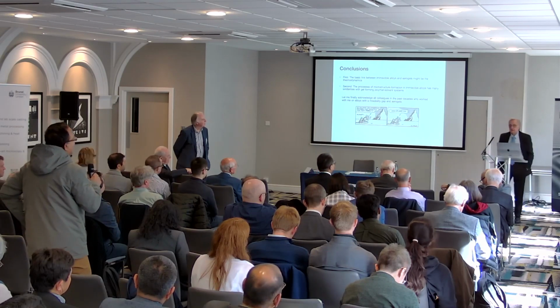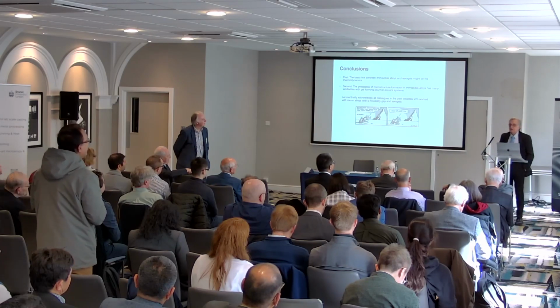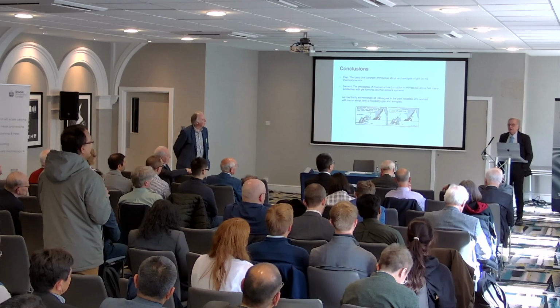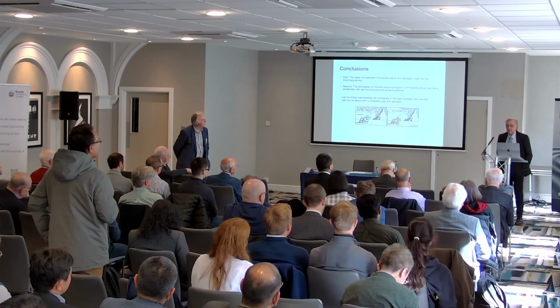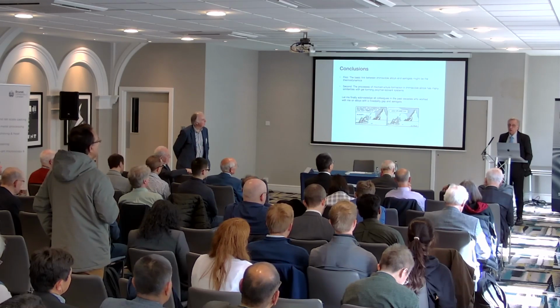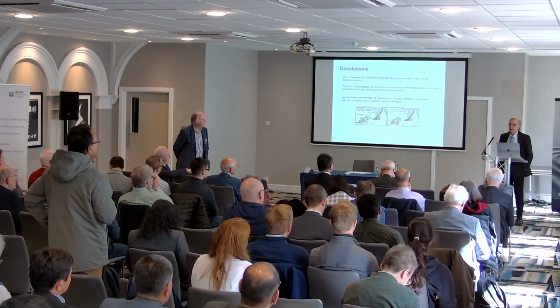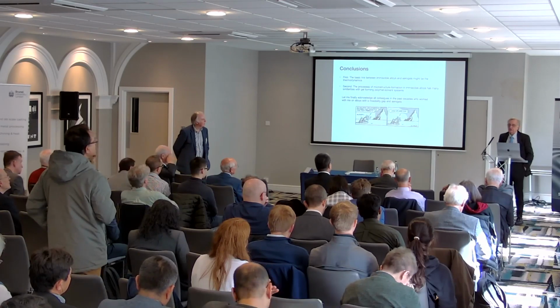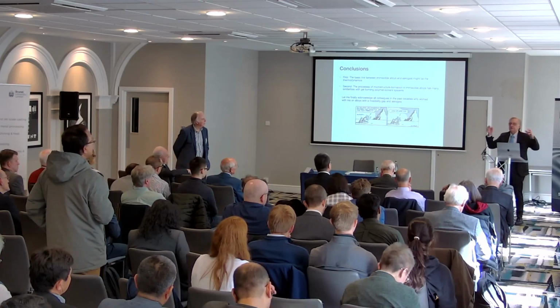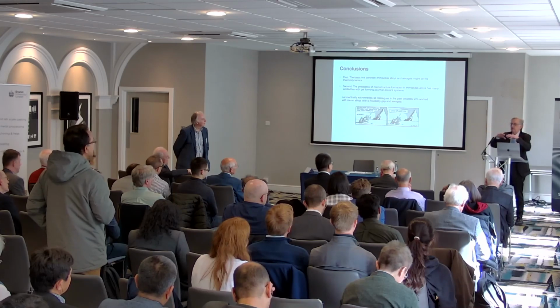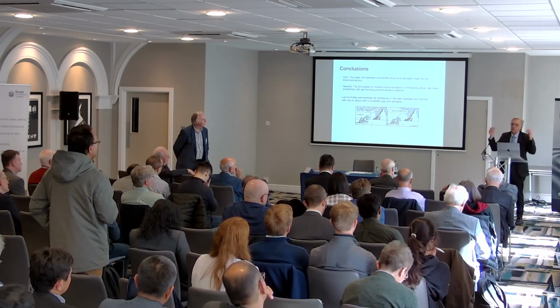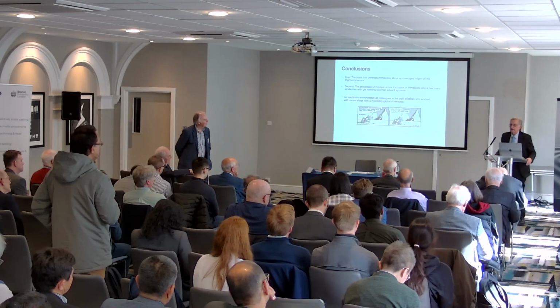So I never studied any system close to the critical point. Besides, my colleagues did that for the metastable miscibility gaps, copper-cobalt, copper-iron, and they always saw droplets appearing, not this famous interconnected two-phase model proposed by Cahn and Hilliard.